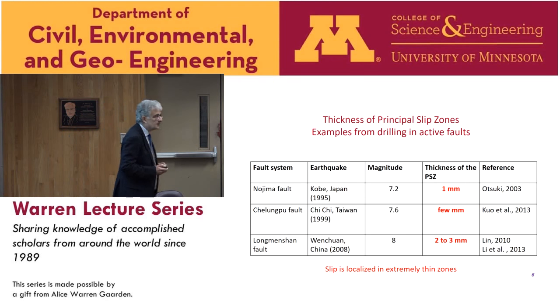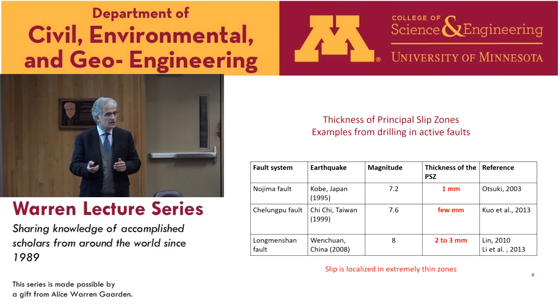This is what is observed from exhumed faults, but the same observation is made in deep drilling programs into active faults. I have taken some examples here of large earthquakes with magnitude bigger than 7: Kobe in Japan, the fault system of Nojima; Chi-Chi in Taiwan, the Chelungpu fault; Wenchuan in China, the Longmenshan fault. All the observations from the drilling into these faults evidence that the thickness of this slipping zone is of the order of 1 millimeter. So slip is actually localized in extremely thin zones.